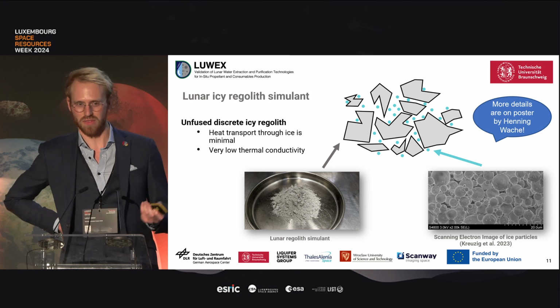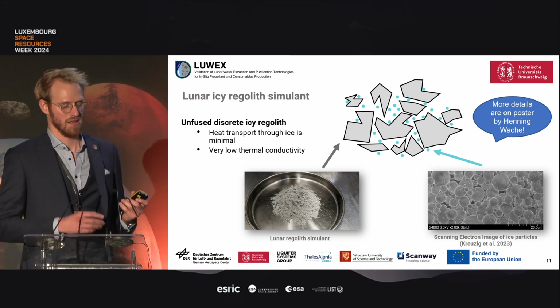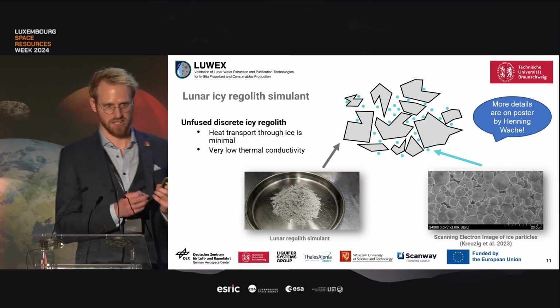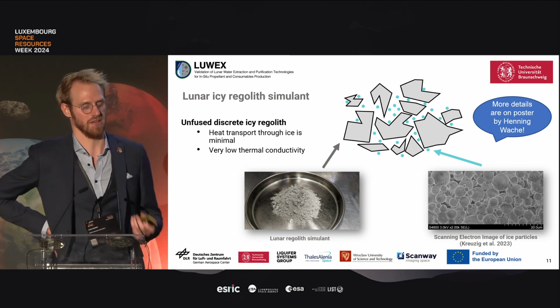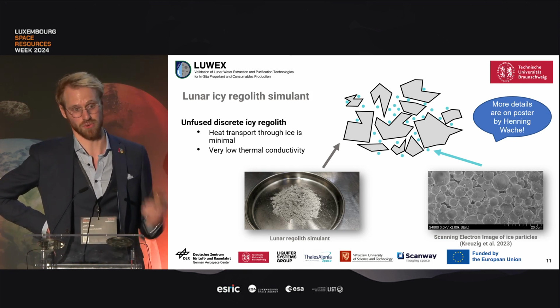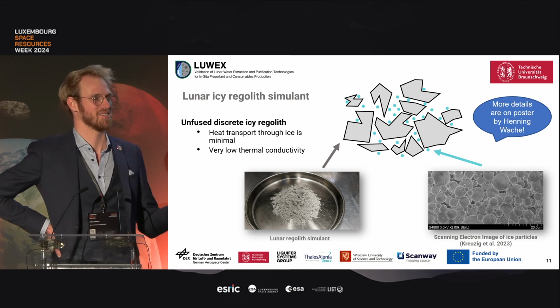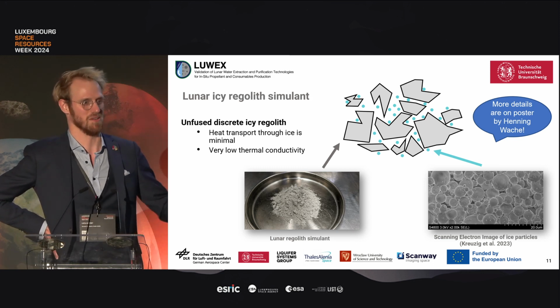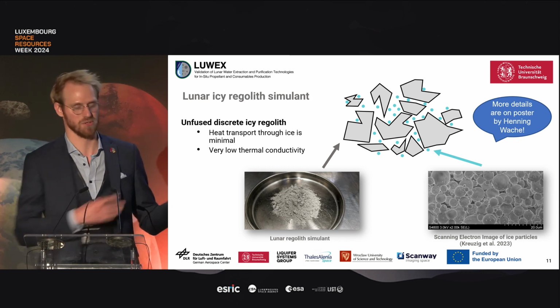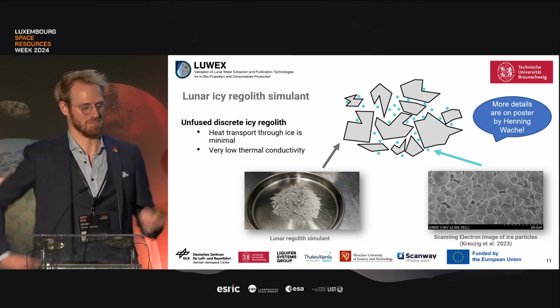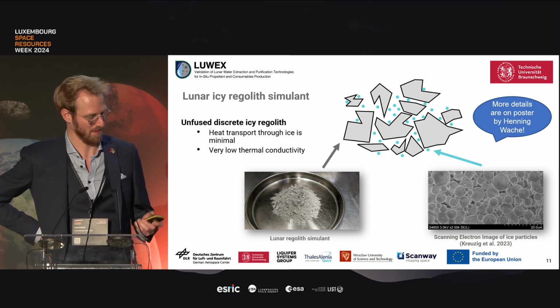The reason we want this kind of simulant is because there is not really any binding between the ice and the regolith, and therefore the heat conductivity is at its poorest. So if we can extract the ice successfully in this case, then if the ice is a bit fused with the regolith, it will always be better. So this is the worst case, essentially.